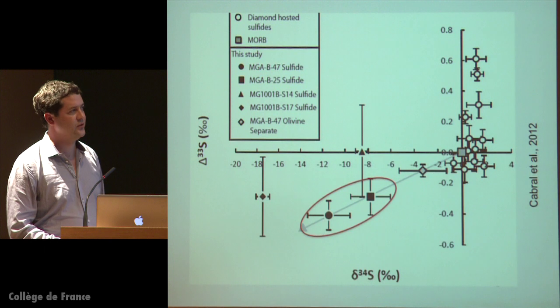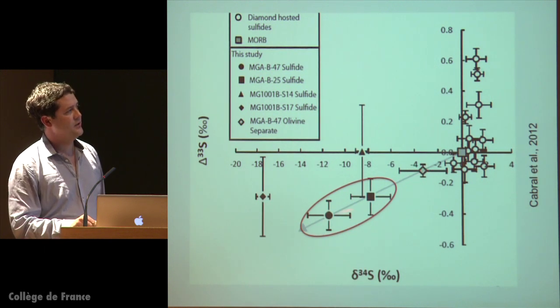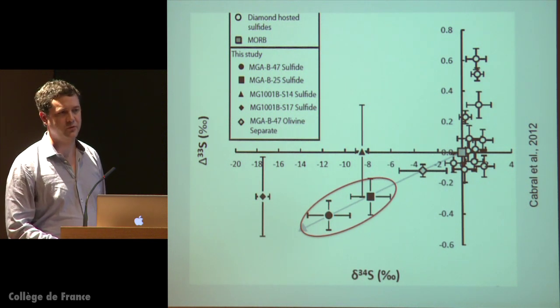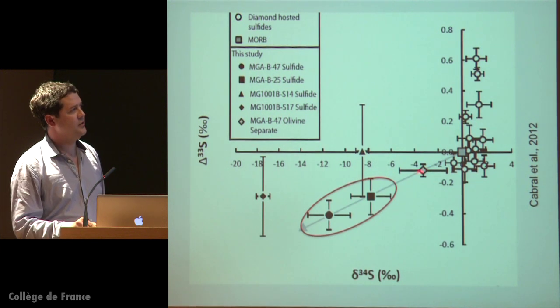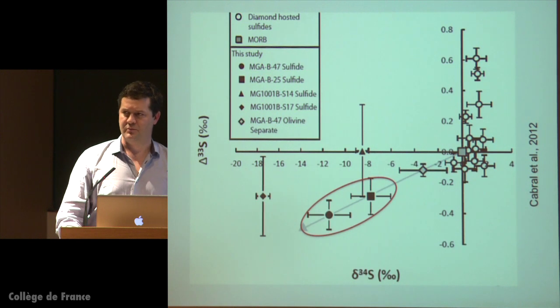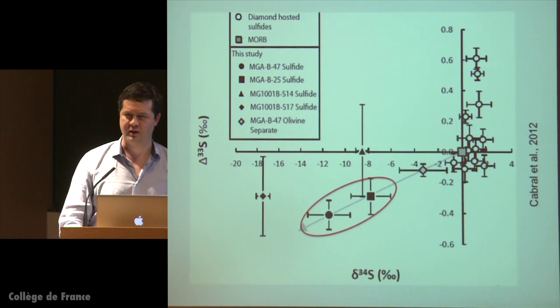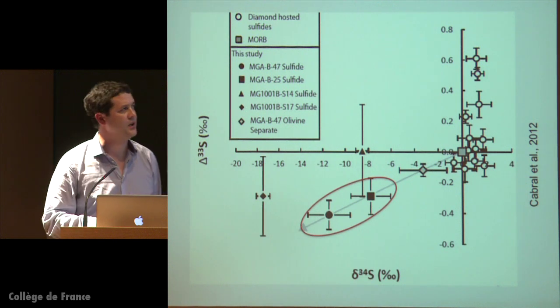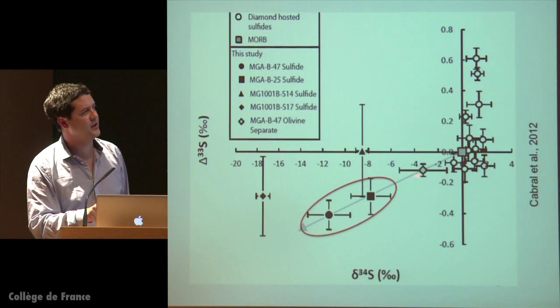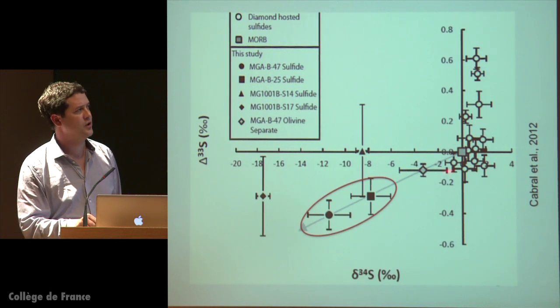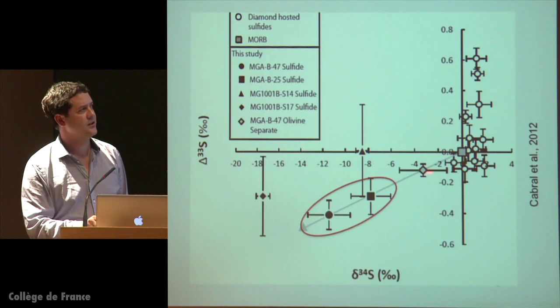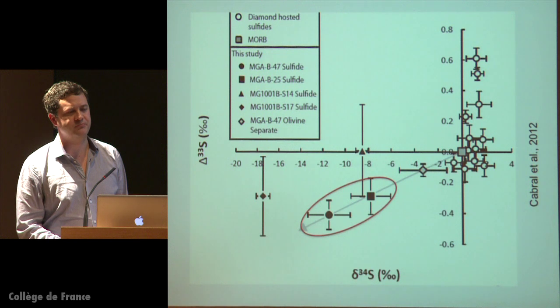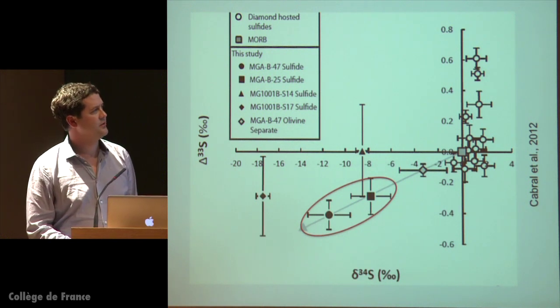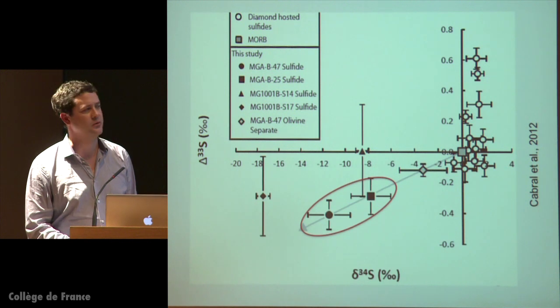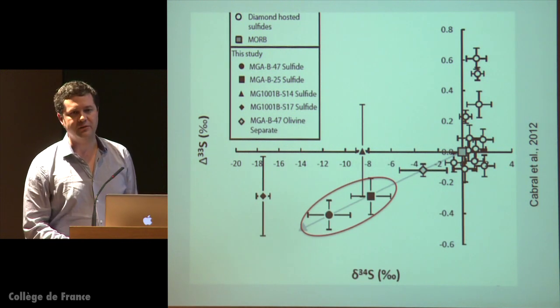So, of course, pretty excited about this result. We'd certainly like to find more sulfides. These 2 sulfides were from 2 different hand samples. Sulfur is incompatible in olivine, so the sulfur in a pure olivine separate should be tied up primarily in sulfides hosted in the olivines. So I picked half a gram of olivines, and James Farquhar ran them and found a small but resolvable anomaly in the olivines. Right now, James is going to make 5 more measurements of olivine separates from lavas from this hotspot, and we hope to see more variability.